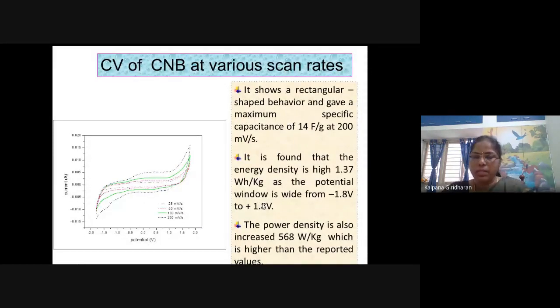This is the specific capacitance from the cyclic voltammogram, and we have obtained 14 farads per gram at 200 millivolt per second scan rate. The energy density is around 1.37 watt-hour per kg, as the potential window is very wide.